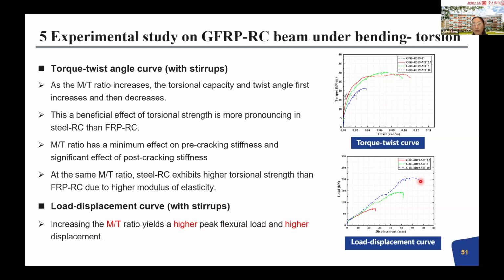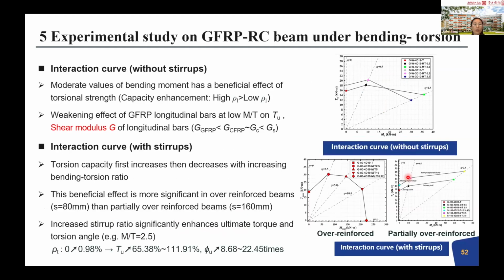And here for the flexural behavior, with increased bending, it will have a higher flexural load and a higher deformability, and more elastic or linear behavior will be observed in the flexural behavior compared to the twisted behavior. So based on the test, we are also interested in the interaction curve.